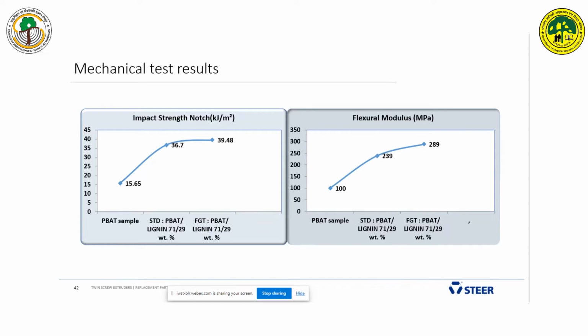Even for standard and FGT, both show an increase in the impact strength, and flexural modulus also increases. In the PBAT virgin, we have 100 MPa, but there is an increase, almost 3 times, when using FGT, which gives you the increase in modulus.